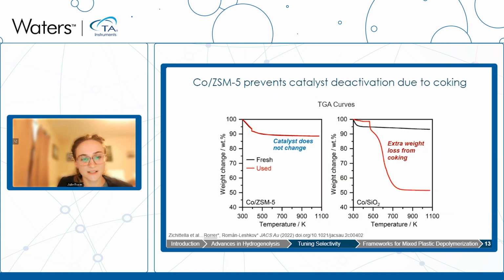And what's interesting too is that by supporting the cobalt on the ZSM5, we improve the catalyst stability. So if we look at thermogravimetric analysis curves of the cobalt supported on ZSM5 before and after the reaction, we see very minimal change or no change at all in the catalyst TGA curve.